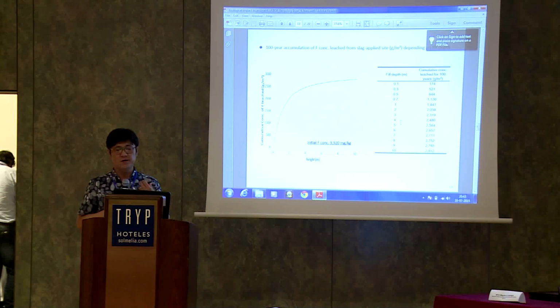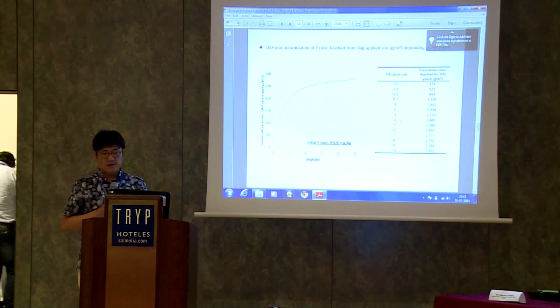This shows a little more practical numbers about the long-term leaching. So if we project the 100-year accumulation of fluoride leached from the slag-applied site, the dimension is expressed as gram fluoride per square meter of the site where the slag is reused. And the cumulative increase was observed, but it's not linear. So when the fill depth is 1 meter, about 1,400 of fluoride was leached from the site per square meter. But when you fill 10 meters as a fill depth, about 2,800, so about double. So the cumulative behavior is not linear, it's saturated kinetics.